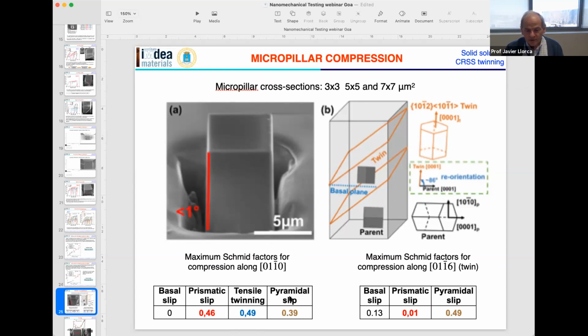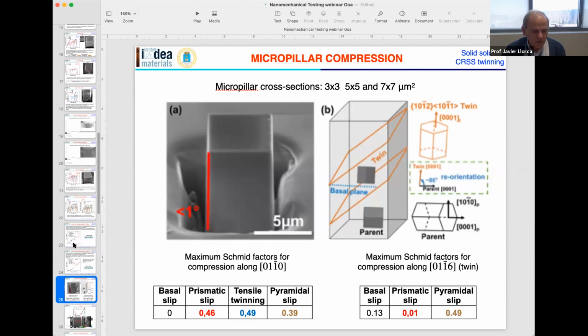One thing that is important that you have to realize is that when you nucleate a twin, it rotates the lattice. So after twinning, you have a crystal with a different orientation. In this crystal with a different orientation, you may have pyramidal slip because the Schmid factor for pyramidal slip has increased in the twin crystal. And also you have a non-negligible Schmid factor for basal slip. In the untwinned material, or the parent material, the Schmid factor for basal slip was practically 0, so you cannot have basal slip. But in the twin material, you may have basal slip. So this is a much more complicated phenomenon, and the analysis of these results is much more complicated.